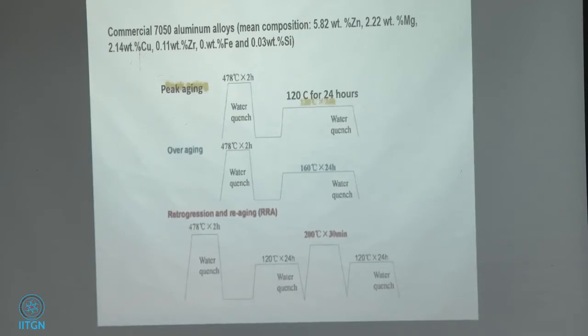Water quenching? Not really, no. You can air cool it also, but not furnace cooling. You can take the sample out and put it in the air. If you quench it, you're freezing everything, basically, which is okay. You won't form martensite if that's what you're thinking. Yeah, after aging, water quenching is fine. Air cooling is also okay. But this is not a big temperature, 120.